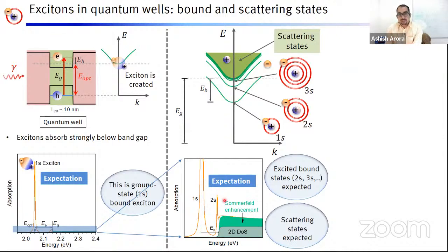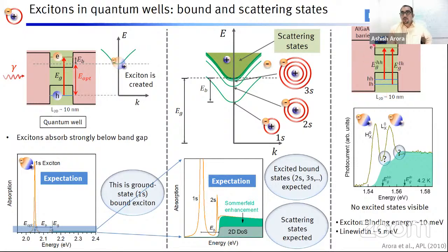So what we expect is these excited states of excitons, and we also expect a two-dimensional step-like feature, because now this is a two-dimensional semiconductor. So you expect a two-dimensional density of states contribution to the absorption spectrum, but this is enhanced due to this Coulomb scattering, and this effect is called Sommerfeld enhancement. But the point is that in the real spectrum, this is expected to decay a bit from the band edge due to this Sommerfeld enhancement factor. Now let us look at the experiment. So we have this quantum well where there are two types of transitions, two types of holes actually, called heavy holes and light holes, due to hybridization of p orbitals in the valence band.